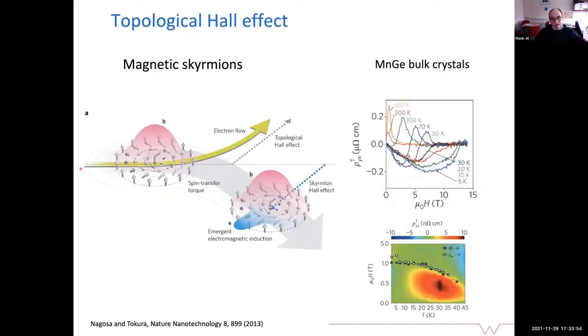Anyway, the idea is that if the electrons flow through these skyrmionic systems, you have a momentum which is given to these electrons. The electrons will act as a wave, as we know, not only as a particle but also as a wave. And they will get a phase shift during the interaction, and whenever this phase shift reaches 2 pi, they will get a momentum. So the interaction between the electrons and these topological structures will give an additional scattering, an additional momentum, which would deliver this additional peak in the resistivity. And then you see here exactly how the phase pocket may occur and so on and so forth.